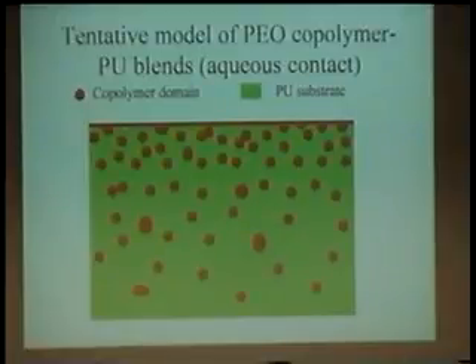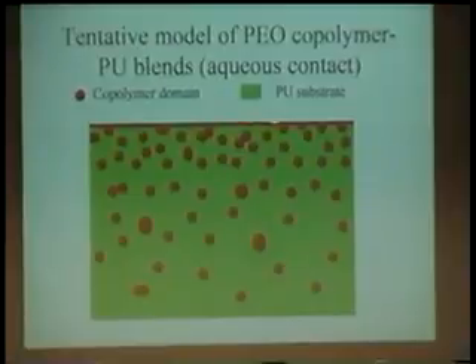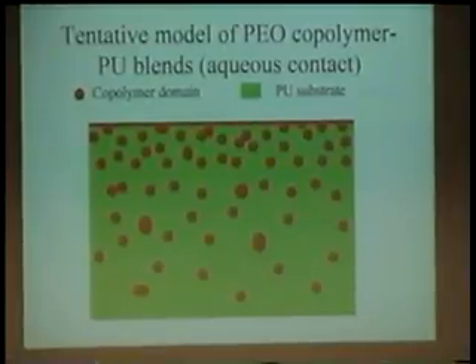And so what we're saying, I think, is that right at the interface here, there's something that's equivalent to a complete layer of the copolymer. And that's what gives us a very high protein resistant characteristic. Of course, if you extract this with toluene, that will be removed, and you'll be left with the pit sort of distribution that you see. Anyway, that's about as far as I can go with that.